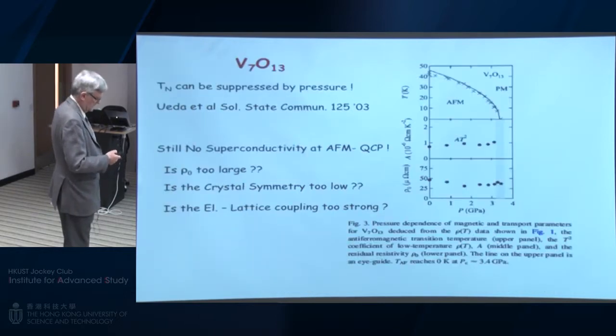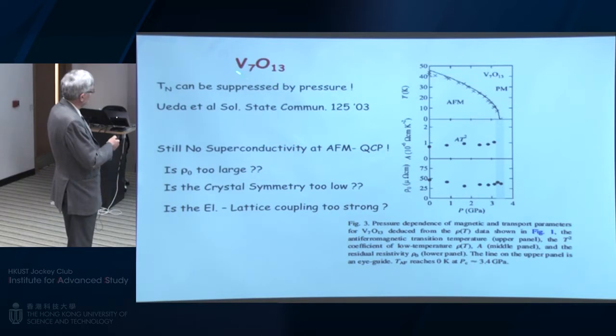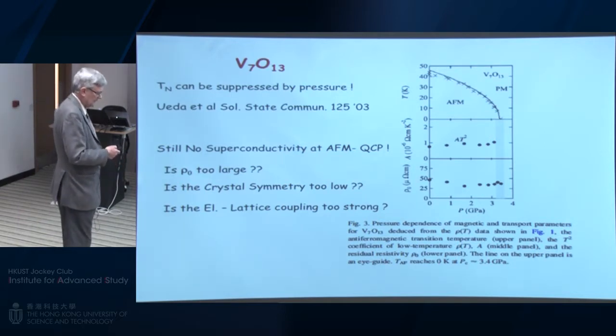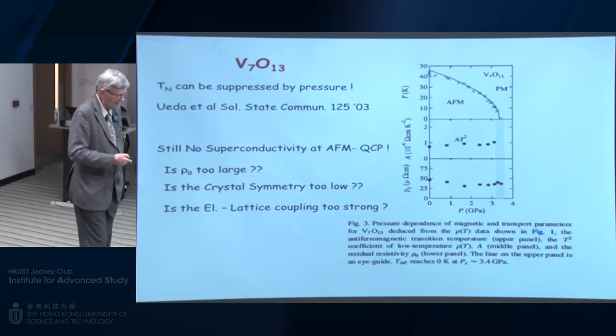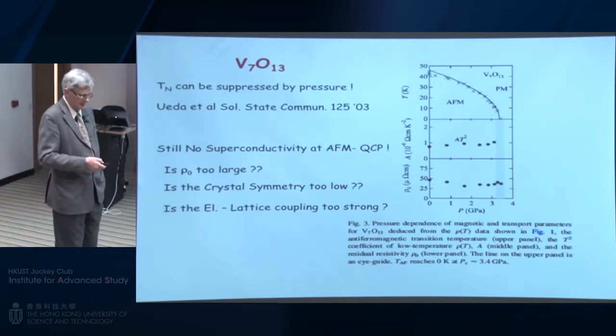And it gets even worse. If we can put pressure, people then later put pressure on this phase here. It's an antiferromagnetic metal. They could suppress it. It keeps a T-squared law at low temperatures, which indicates it should be some kind of, or signs of a Landau Fermi liquid. And in many cases, I didn't mention it earlier, but in the heavy fermions, when you get rid of antiferromagnetism, that's when you get superconductivity. No such luck here. So you see that this 3d1 and 3d9, the crystal chemistry is very different.